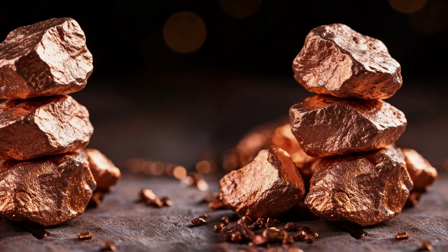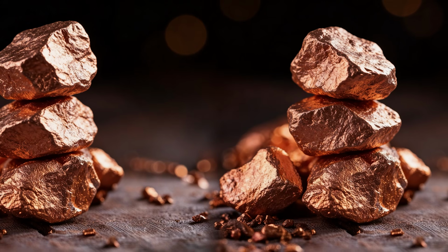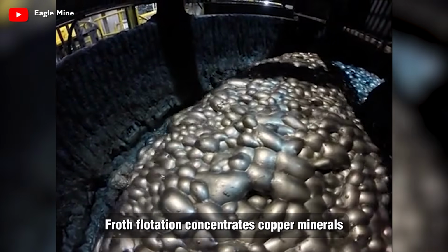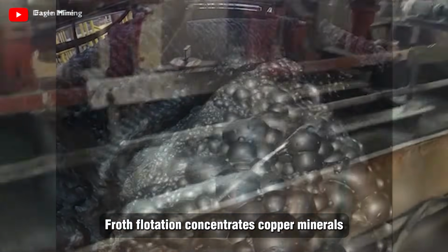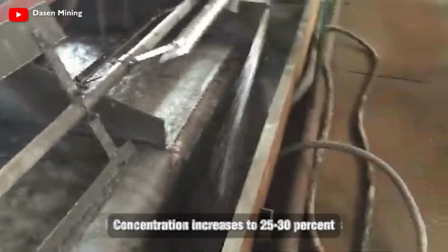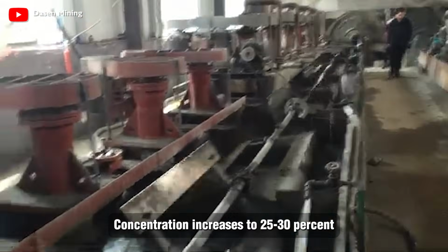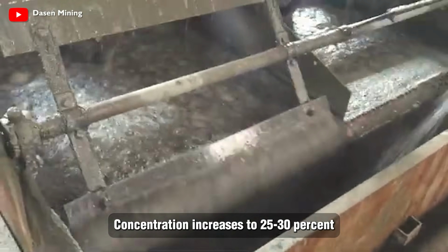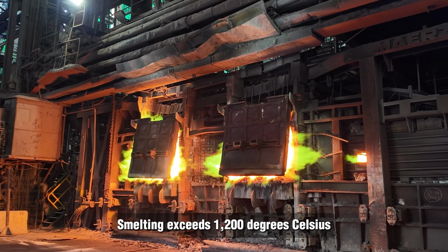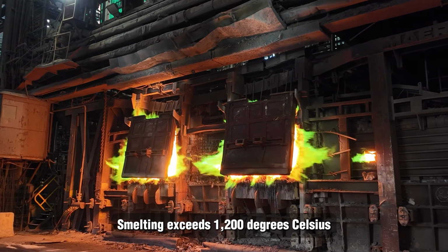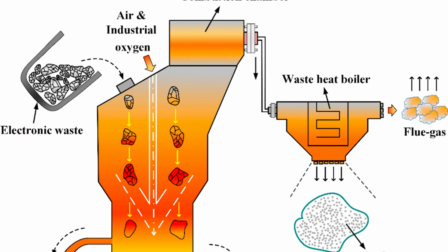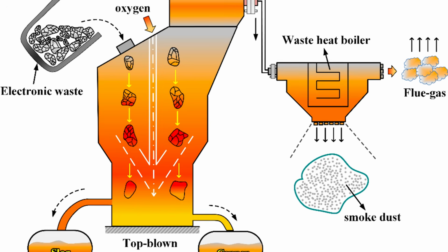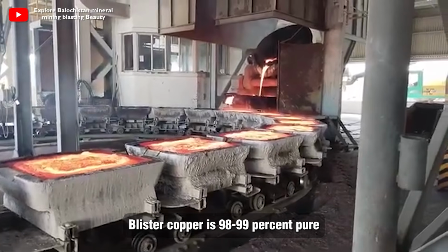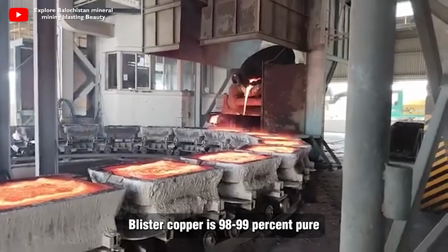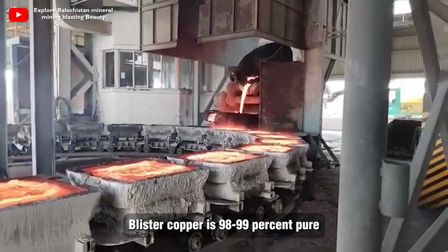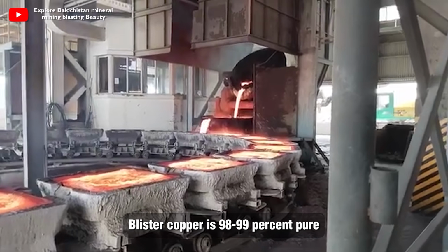Transforming copper ore into pure metal requires multiple sophisticated processing stages. Crushed ore undergoes froth flotation, where chemicals and air bubbles selectively attach to copper mineral particles, concentrating copper content from roughly 1% to approximately 25 to 30%. The concentrate then enters smelting furnaces, where temperatures exceeding 1,200 degrees Celsius melt the material and separate copper from sulfur and iron compounds. The resulting product, called blister copper, contains 98 to 99% pure copper, but still requires further refining for electrical applications.